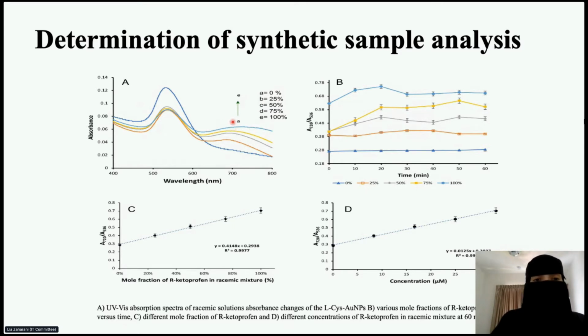So the new peak here increases, and this one decreases. Also, I investigated the percentage versus time. As the percentage increases, the absorbance increases. However, it's not related much to time. C is the mole fraction of R ketoprofen in the racemic mixture versus the absorbance of this peak to this peak. And this one is the concentration of R ketoprofen versus the difference in absorbance between this peak and this peak.